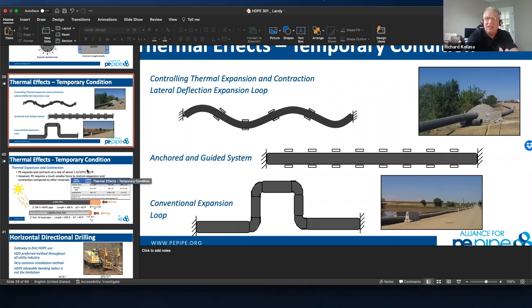And here's the beautiful thing about it. Although it moves, it will never fail by fatigue. And that is a concept that everybody has a hard time with. We do not fail by fatigue. So if we expand it and contract it, we do not see failure in polyethylene because it goes back to its normal state. You're not ripping apart the polymer, but if you did exceed that yield, then you've just overpressurized.